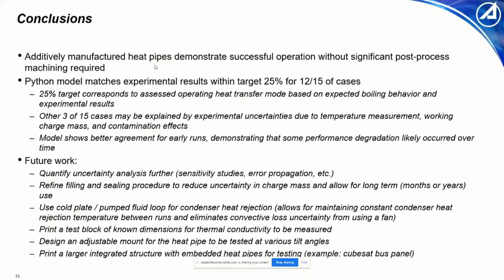We also want to print a test block of known dimensions for the thermal conductivity to be measured and design an adjustable tilt mount for the heat pipe to be tested at various angles, corresponding from reflux mode, which is what we assessed here, all the way to horizontal and potentially even adverse tilt angles. Doing that would just expand our testing capabilities significantly.